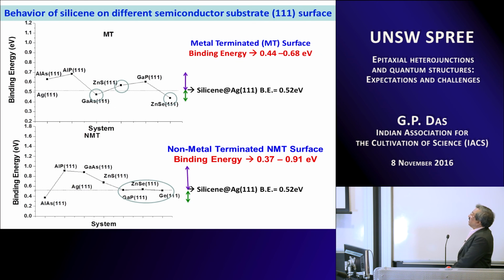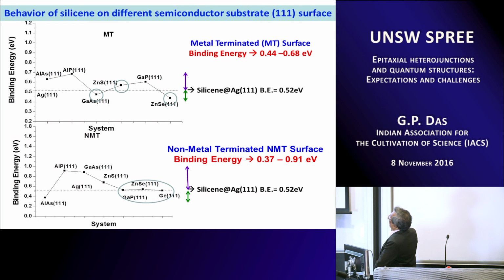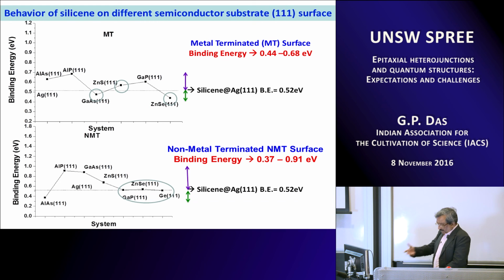Now, thankfully, the lattice parameters of silicene with most of these III-V and II-VI semiconductors are reasonably good, not exact, but reasonably good. So here is how the binding energy of the silicene layer epitaxially grown on the III-V and II-VI semiconductors behaves. These are the numbers you can see here, and this line is the binding energy for silicene on silver 111, which Gilles' group have got. So 0.52. Whereas our results, the binding energy varies from 0.44 to 0.68 electron volt.